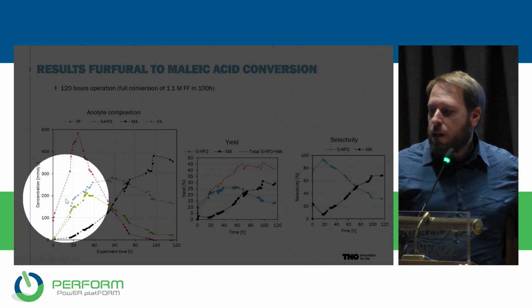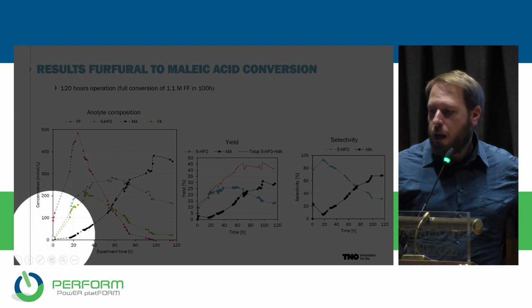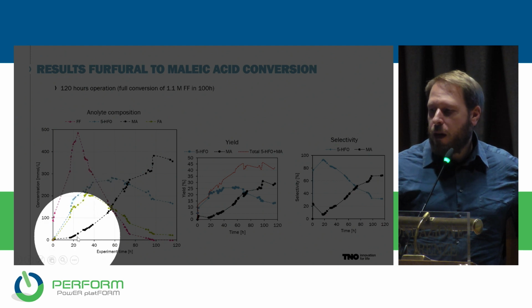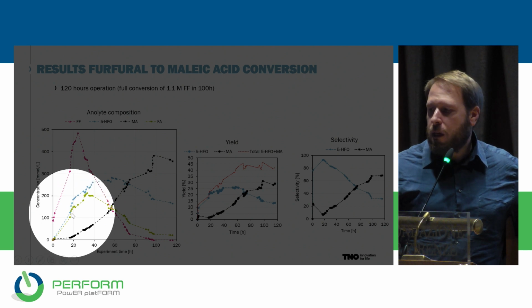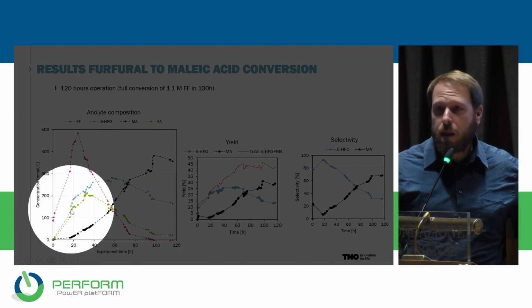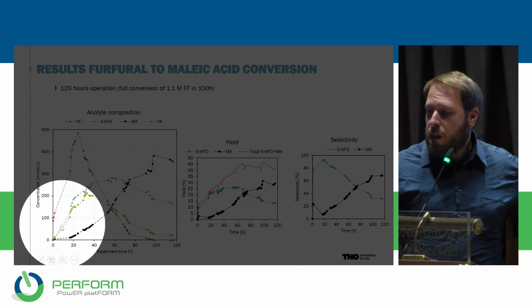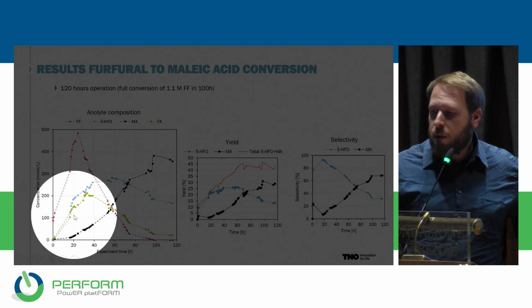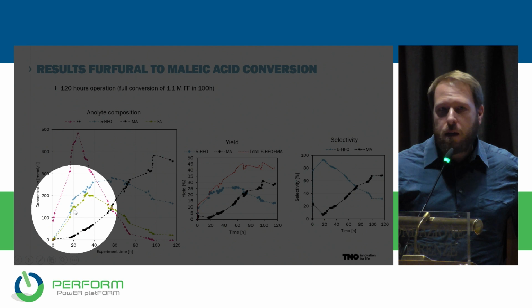you see that with the blue line, the first thing that we make is 5HFO. And at the beginning of the reaction, we have no maleic acid production. So this is actually in agreement with the mechanism that we envisioned before, especially because we can also show that together with 5HFO, we also make formic acid.